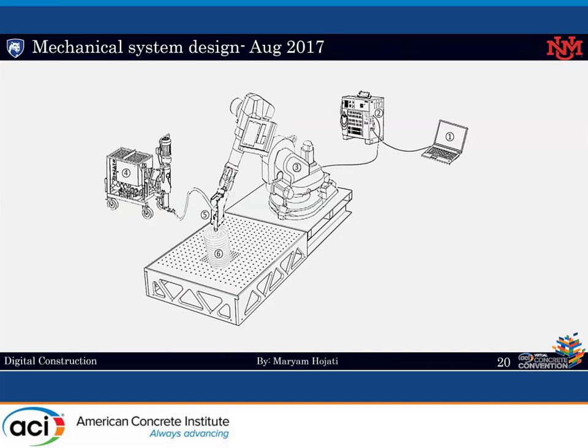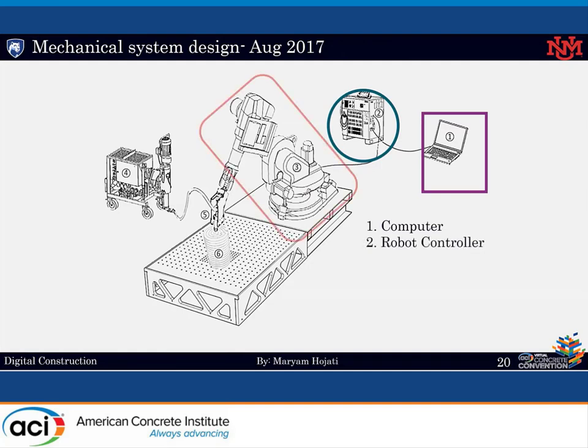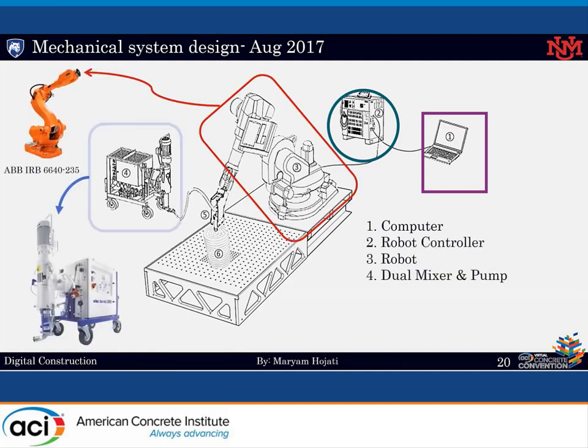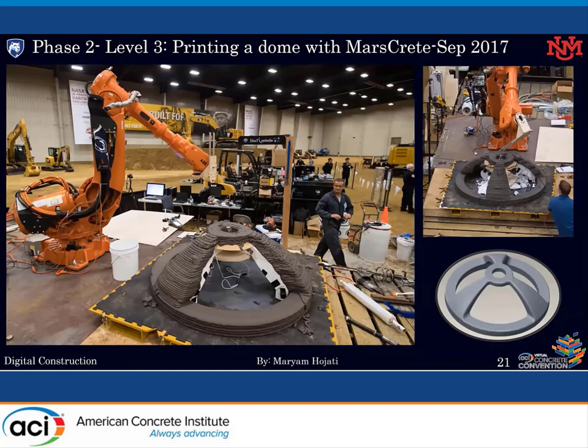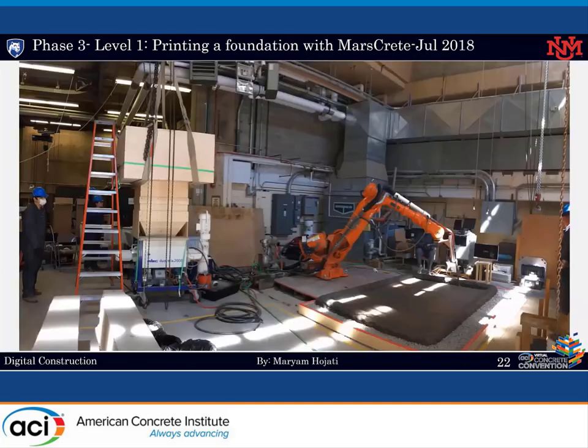For third level of phase 2 of NASA project, we upgraded our printing system and used a larger robotic arm together with a dual system of mixer and pump that you can see in this slide. This slide shows the dome which was 3D printed in the last level of phase 2. As you might see, some foam work was also used but finally removed by the robot after material was set.